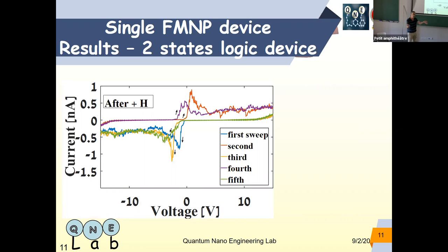You can switch the magnetization from up to down depending on the current direction and the size of the current. So you can do it in a very, very simple way, and it's much simpler than standard spintronic devices. If you want to know why it is not going to industry, the main problem is that so far we use molecules. Molecules do not stand; they cannot go higher than 100 Celsius. The industry uses oxide, which should go to 500 C. And now we are developing chiral oxide that can solve this kind of problem.